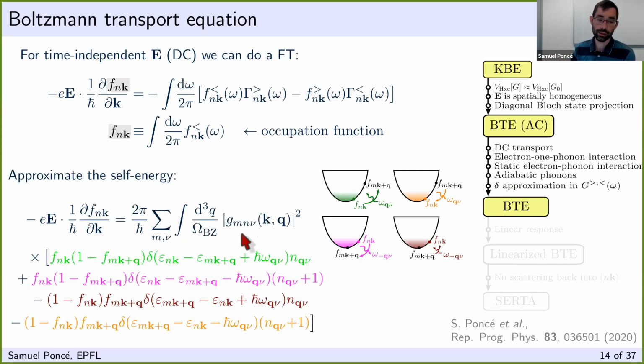If we do all of those approximations, then we can simplify this collision term, and we can show that this is equal to the electron-phonon matrix element times those 4 energy-conserving terms. Those correspond to those 4 situations where you basically have an electron or a hole leaving the state Fnk by absorbing or emitting a phonon, and you have the reverse. You have an electron coming inside the state Fnk by absorbing or emitting a phonon. So those are the 4 possibilities, and they are described by those 4 lines.